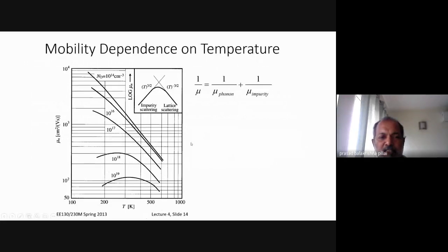So this is a picture. One can demonstrate the variation of impurity scattering with temperature in this fashion: the impurity scattering will cause an increase by this factor, whereas if lattice scattering is dominating, the variation with temperature will be like this. So you can see that the mobility at low temperatures increases and is dominated by impurity scattering, whereas at room temperature and above, it is dominated by lattice scattering. This gives us an idea about the mobility variation with temperature, because the whole idea, from the very first lecture, was trying to find out why the conductivity is changing with temperature.